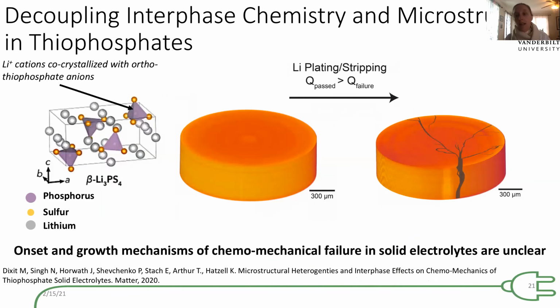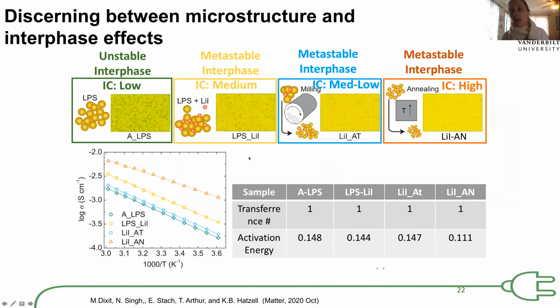We have been really interested in looking at how they fail. What about the microstructure of the solid electrolyte governs failure at lithium metal anode interfaces? Unlike the oxides, which was the work that I was talking about in the lithium metal work previously, these are much softer solid electrolytes, and they can have catastrophic fractures. So we were interested in understanding how the microstructure impacts failure. We designed an experimental protocol with different materials where we processed them to get different microstructures.